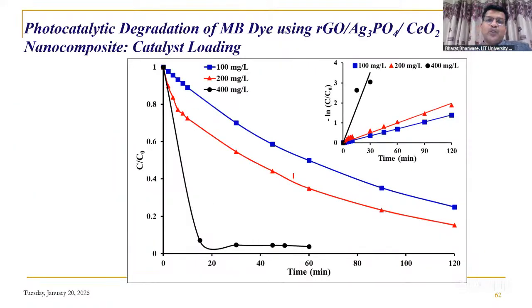We carried out the degradation using this nanocomposite as photocatalyst for MB dye. It is observed that with the addition of this nanocomposite, we prepared the dye solution in water base, added the composite, and exposed it to sunlight. It was observed that degradation is continuous.